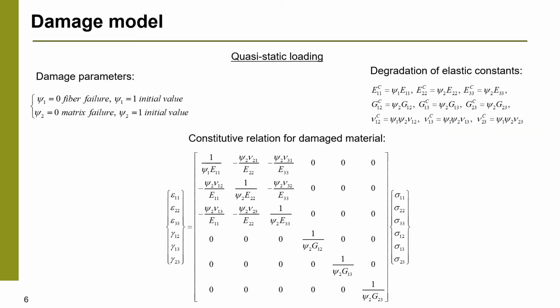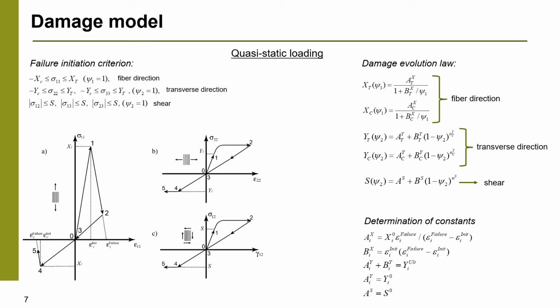This work proposes a model of composite material damage and failure. It's based on the continuum damage mechanics concept. We introduced two damage parameters. Psi1 is associated with fiber failure and Psi2 with matrix failure mode. Damage parameters can be considered as multipliers to elastic constants, and can be interpreted as a degree of material stiffness reduction during damage accumulation. The maximum failure stress initiation criterion is chosen for simplicity, and on these diagrams you can see assumptions for the damage constitutive law.